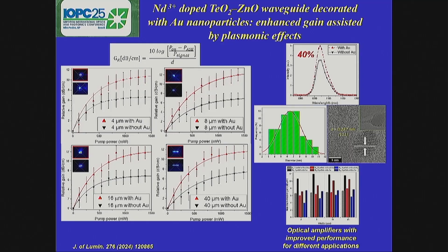We repeated this experiment using different concentrations of neodymium. So instead of using just 1 pellet, we used 2 and 3 pellets of neodymium oxide and repeated the experiment. In this figure, I summarize all the results. In red, we have the results that correspond to the use of 2 pellets. In blue, 3 pellets. Black and gray, the results I showed you related to 1 pellet.